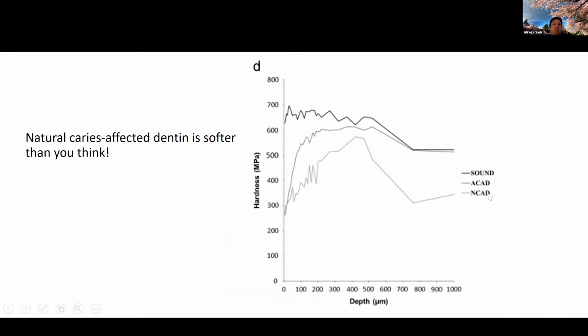And we took a number of natural caries affected dentin, natural carious teeth, recently extracted, and we tried to get them to the test as soon as possible. And this is what the result is. It is very interesting. There is only one peak of hardness in deep caries. There is one peak of nano indentation hardness within the intertubular dentin. And if you miss that peak, then it's going to get softer and softer and softer. Now, can we understand the reason why we come up with pulpal exposures? Just because we go based off the hardness.